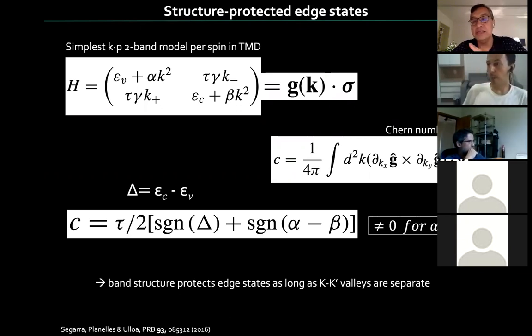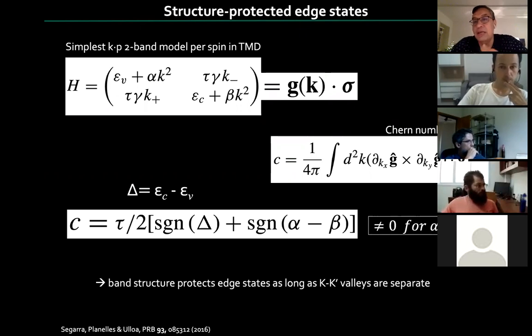This is just the simplest argument: the band structure protects these edge states as long as the valleys don't mix, which is of course an assumption. This is similar to the argument that people make for topological insulators, except that in that case you involve the spin, and so the protection is topological: if you have typical spinless scatterers, they protect that. This is structure protection. Here there is not such protection, because this is per spin species and per valley.